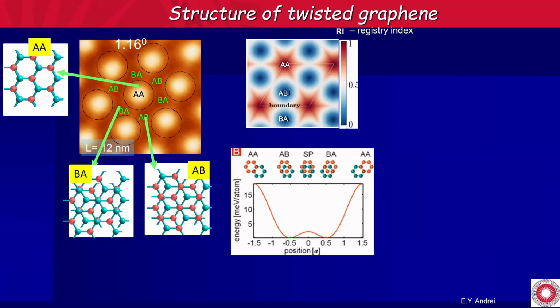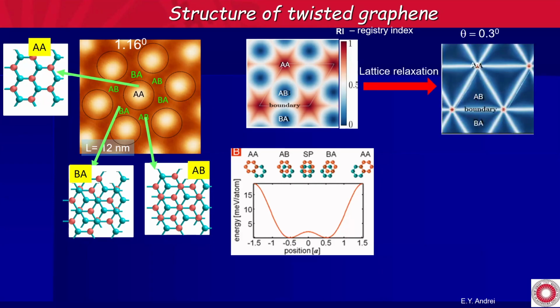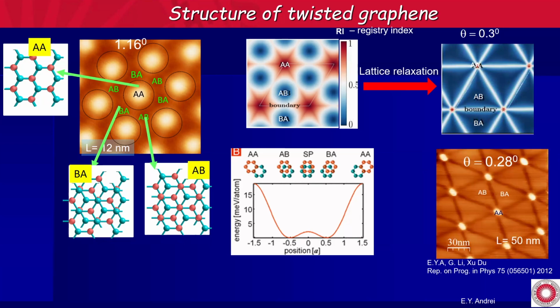So in fact, when you go to small twist angle, where the Moiré is very large, it pays to shrink the AA region at the expense of building up strain. Okay, and that is energetically favorable. And in fact, when you go to 0.3 degrees, these AA regions become tiny. And this is theory, but in experiment, that's exactly what you see. Okay, so there is a lot of action going on in there. It is not a static kind of crystal.